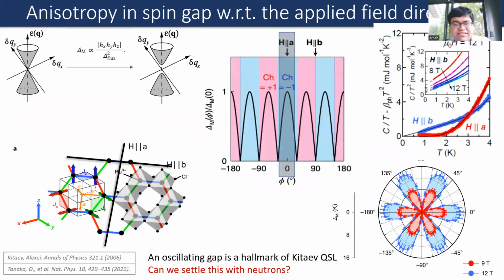There is another very nice, interesting paper which came out, which does heat capacity studies, and they applied the field along those two directions. This is published in Nature Physics by Tanaka in 2022, where they showed that if you apply the field H parallel to A, you indeed have gapped excitations, while if you apply the field H parallel to B, you have gapless excitations. That's very nice. And then they could map out how the phase diagram of gapped versus gapless excitations would look for various directions of the magnetic field, because that also matched with Kitaev's predictions.